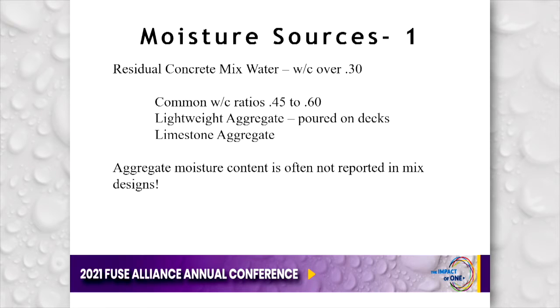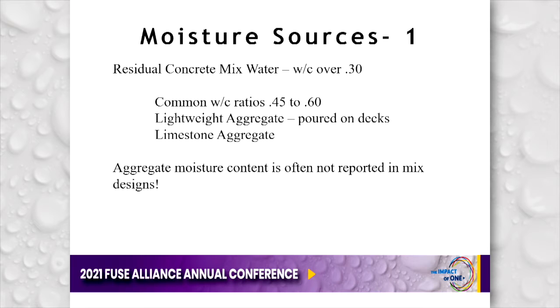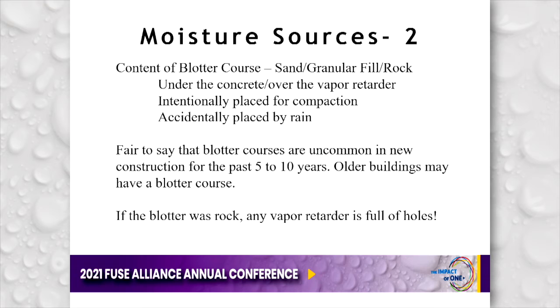And then we see the use, in parts of the country, of limestone aggregate. Limestone aggregate can absorb 3 to 5% of its own weight in moisture. That's differentiated from granite or quartz, which are less than 0.5% of their own weight in moisture. So looking at that mix design and seeing limestone needs to tell us that this concrete is going to take longer to dry than something made with quartz or granite. And again, as I've just said, aggregate moisture content is typically not reported in the mix design.